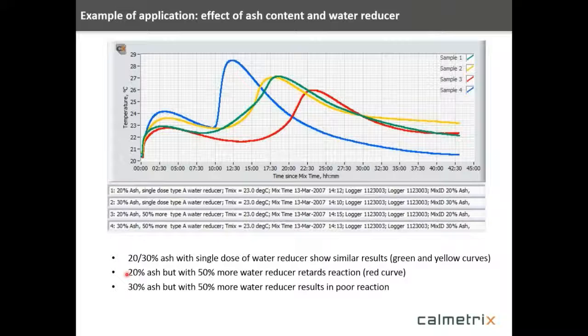The third curve here, the red curve, has 20% ash, but now with 50% more water reducer. So in this case, the reaction has been retarded, but the shape of the curve is still normal, but simply retarded. But now when we go to 30% ash with 50% more water reducer, the reaction suddenly does not go very well. This is an indication of a poor reaction. The interaction here is not good, and so you can very graphically tell that this would not be a good mix in the sense that the reaction is a poor reaction.